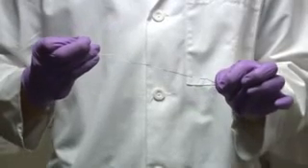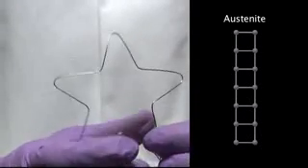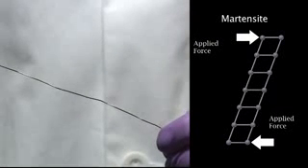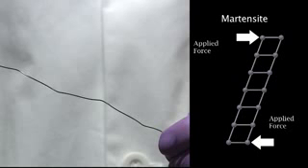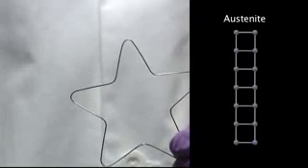This also works because of phase transformations. This material is a slightly different composition, so that at room temperature, it is in the austenite phase. If we stress the material, we can force it into the martensite phase, and this will change the shape. But if we release the stress, it goes right back to the austenite phase, and the original shape, because that is where it is stable at this temperature.